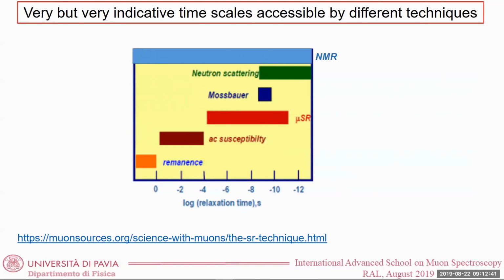Of course, from this, you see that I am an NMR guy. But the point is that at the end, there is no problem in measuring relaxation rates which last hours, and there is no problem in measuring dynamics which are of the order of 10 to the minus 14. It has been done in many cases, and it depends a lot on the experiment. So this comparison of time scale should be taken with care, and it depends a lot on which type of experiment you are doing.